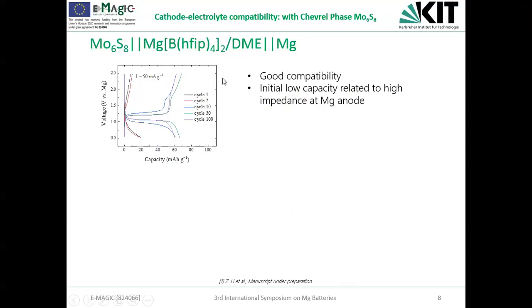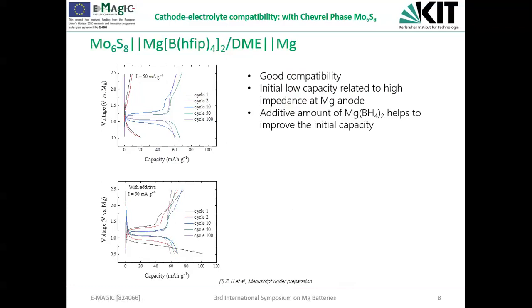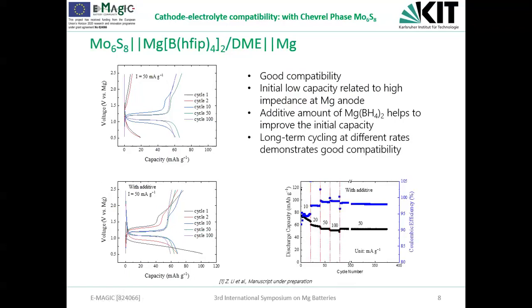And here, in order to deal with this problem, we also tried to introduce an additive amount of magnesium borohydride to the system, hoping that it could somehow clean the magnesium surface. And the cell indeed shows a good capacity and distinct voltage plateaus, even in the first cycle and onwards. So this means it works. Also, in long-term cycling at different current rates, we see that the cell could be cycled for more than 300 cycles, and this also means that a trace amount of magnesium borohydride will not affect the long-term cycling, which is also something I want to mention.